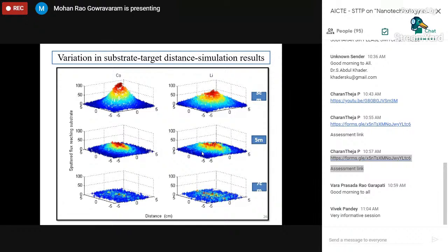The fat fellow will lose all energy fast. So halfway he loses energy. He will not be able to move further. So it means that if you keep your substrate far away from the target, then what you get will be only lithium, but no cobalt in that. So if you have to get both lithium and cobalt into your film, the target to substrate distance has to be optimized.